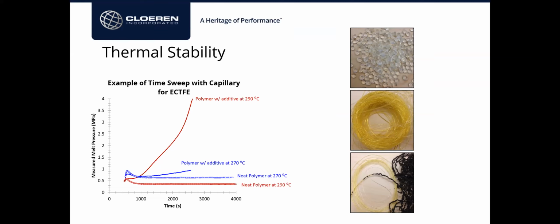What is the best method to measure the viscosity of a two-component material in a capillary rheometer without pre-compounding? For example, glass-filled material added at some percentage. I think the best way would be, if possible, to do some sort of in situ measurement from the extrusion, where you compound the material, and with the same compounding machine, if you were able to attach a rheometer die online and do the measurement there, that would be the best way. However, you could also compound the material with a specific machine that's representative of the extrusion process, collect this material sample, and then measure it in a capillary rheometer. That will work as well.